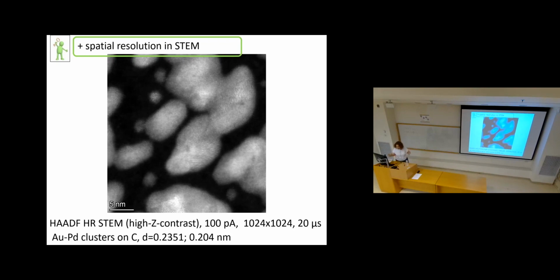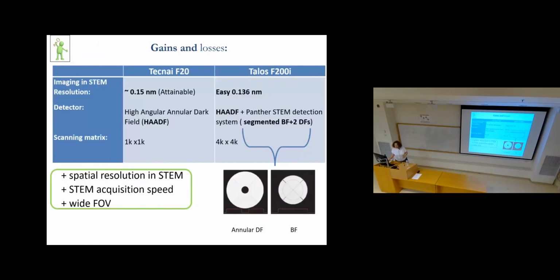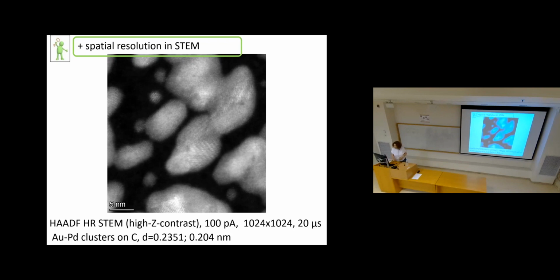So we gain here a huge amount of abilities with the high resolution scanning transmission electron microscopy, because the resolution and the ease of acquisition is much more advanced than we had with the F20. But not only this gain we have, so the acquisition speed is also faster, and we can acquire that. I mentioned there that this image was acquired at 100 picoamp of current, with a quite coarse matrix 1K by 1K, with a dwell time of 20 microseconds per pixel.